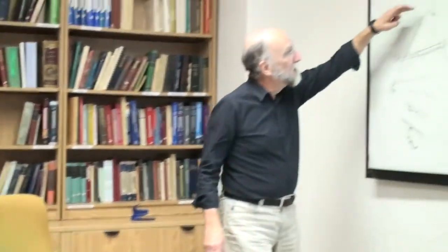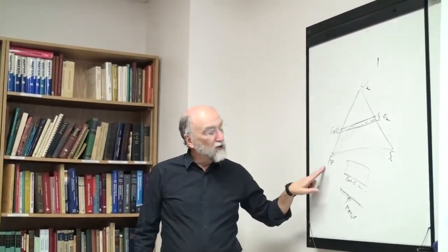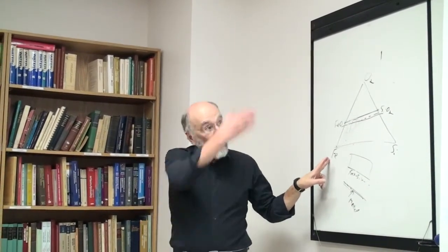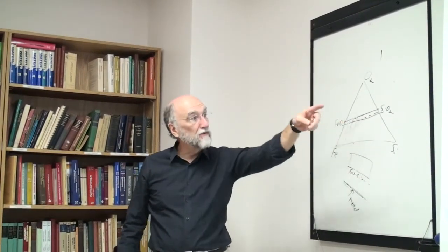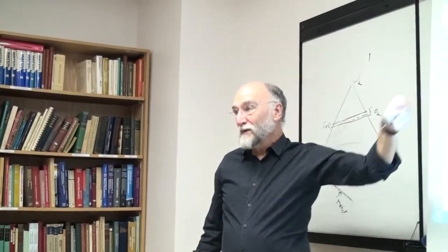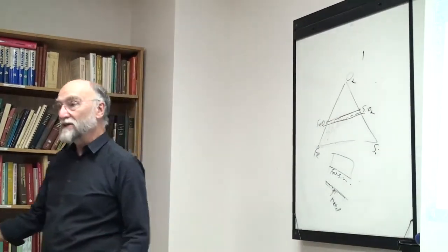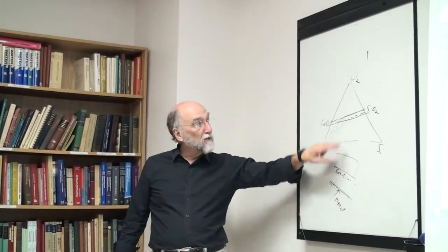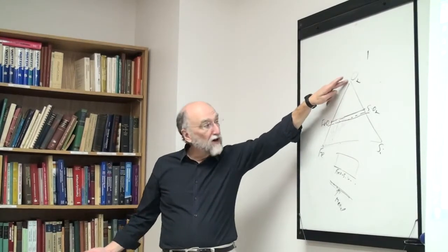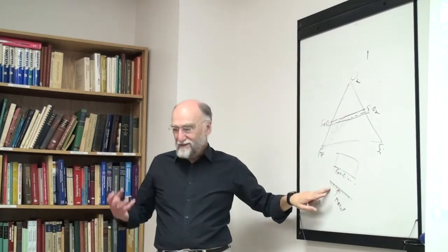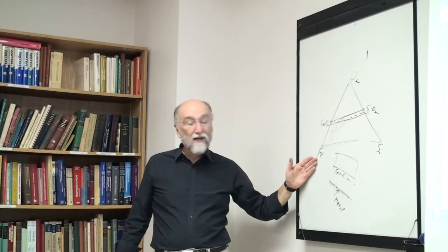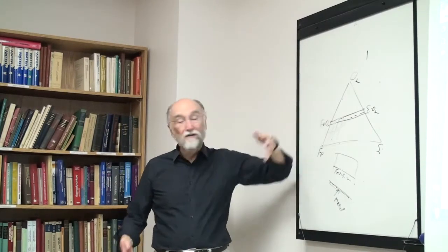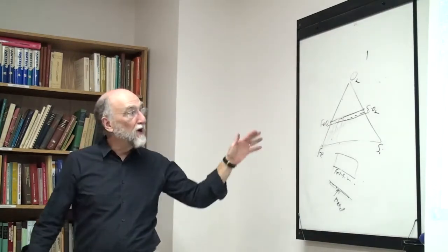Now, of course, if you really want your hypothetical diagram at constant unit iron activity, you could still have a diagram, oxygen, iron, sulfur, in equilibrium with pure iron at unit activity. And you could calculate the diagram theoretically just the way we did the other one, fixing the activity of iron equal to 1. But that would be very hard to realize in a practical experiment. You could keep your oxide phases in equilibrium with a PO2, an atmosphere of constant activity of oxygen, but how do you keep it in equilibrium with a metallic phase with the activity of iron equal to 1? You can't really do that unless you have iron vapor or something. So that doesn't correspond to a real situation.